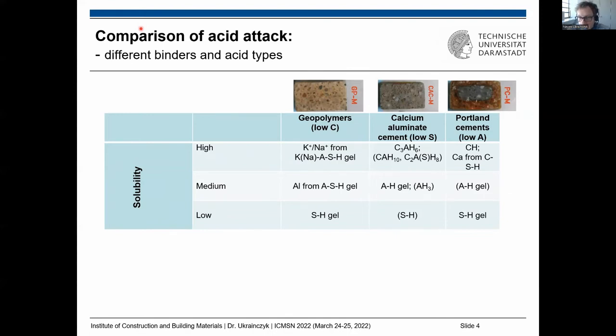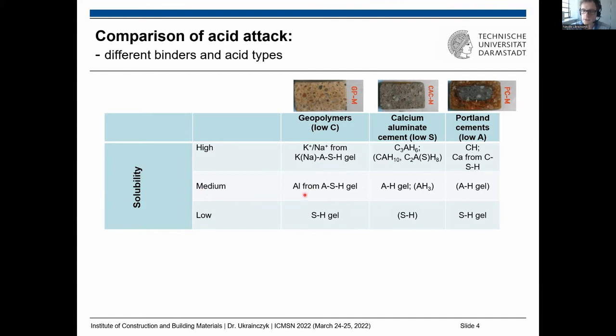Comparing different binder types: our geopolymers have a very low calcium content. If we activate other materials and increase the calcium content, we enter a broader class called alkali-activated materials. Geopolymers are just one class within that — low-calcium alkali-activated materials. The absence of calcium is what makes them very stable with low solubility, because they are essentially zeolites. We observe leaching of alkalis from the zeolite-like gel, then medium incongruent dissolution of aluminum, and finally a silica gel with the lowest solubility.